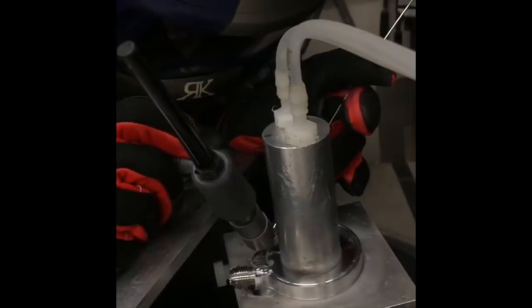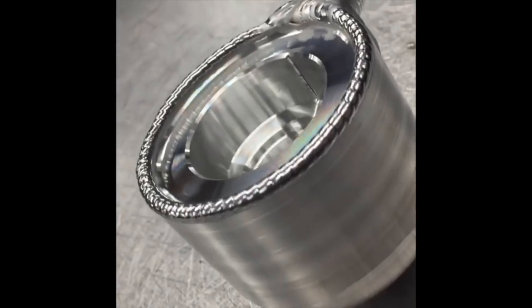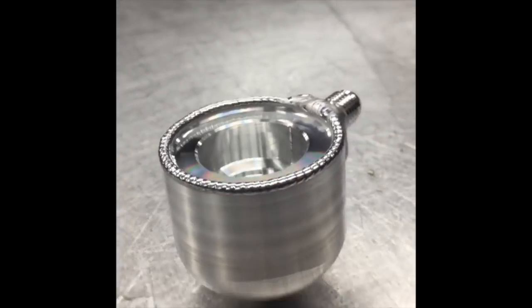Yeah, so with my tungsten prep, I have a dedicated diamond wheel tungsten grinder that I grind with. It puts pretty much the exact same point of whatever I want. I can repeat that anytime I want on my tungsten. I don't know how common of knowledge it is. If you look for it, you can find it out, but how your tungsten grind angle and the type of point that you put on it will affect your arc. It really does affect your arc, and you can use it to your benefit in different situations of manipulating your arc to the type of weld that you want.